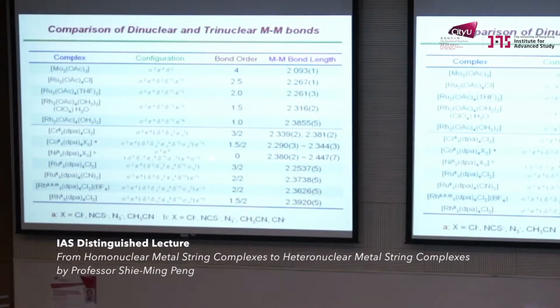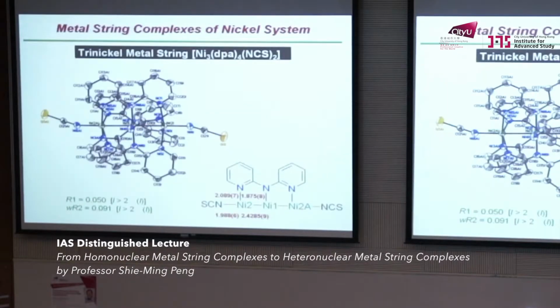But very interesting is that for the trinickel species, the bond order is 0 because you will populate all the bonding and anti-bonding orbitals. Bond order is 0. But from a synthetic point of view, the yield is the highest one. So metal-metal bonding does not contribute to the stability of the metal string. So this is the trinickel species. According to the previous analysis, I should take out these 2 sticks because the bond order is 0. But you know the ORTEP diagram always shows the distance is within bonding, so they draw a bond.